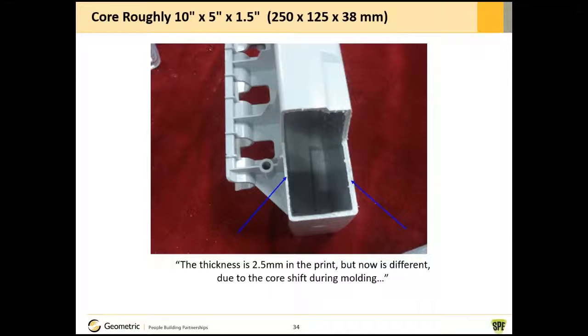Wrong. The 20,000 psi acting on the tip of the steel is making it bend, and this wall on the left is not supposed to be half the thickness of the wall on the right. That has happened because the core, this massive steel core, has shifted. So this rule applies even if you have a big opening in the plastic part, and you need to have a proper consideration of the thickness or the diameter to height ratio.